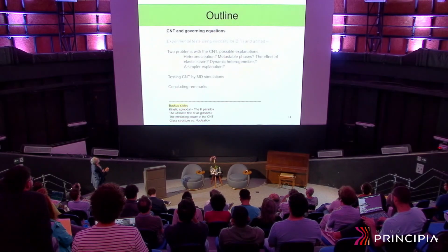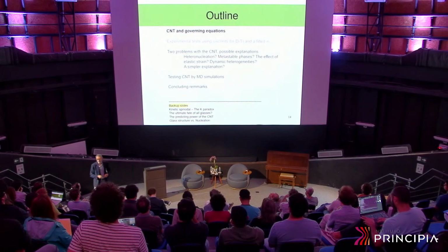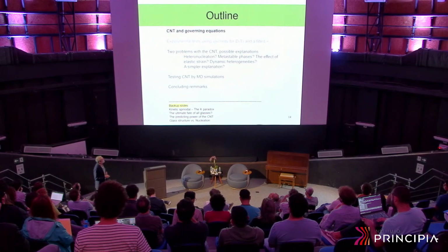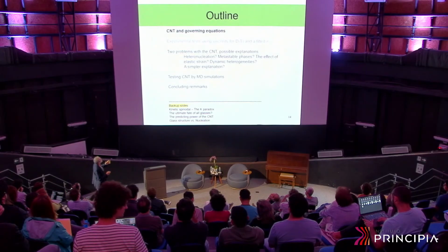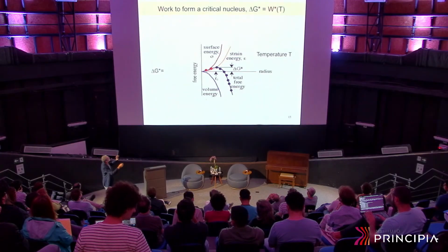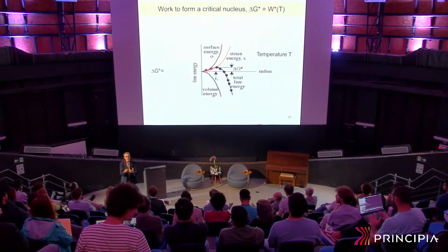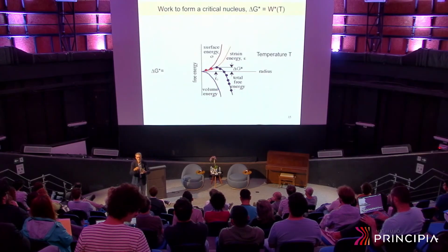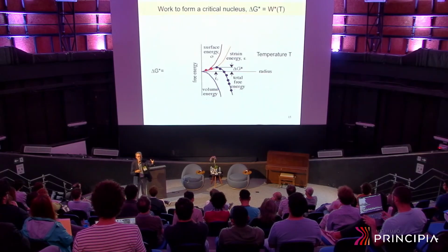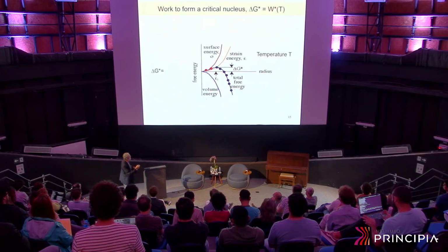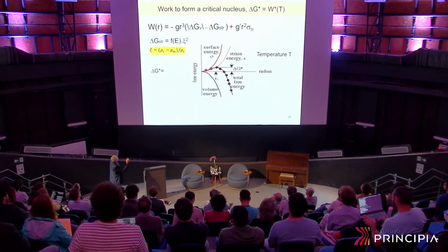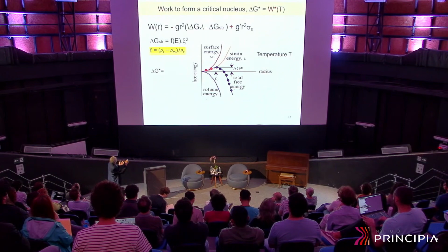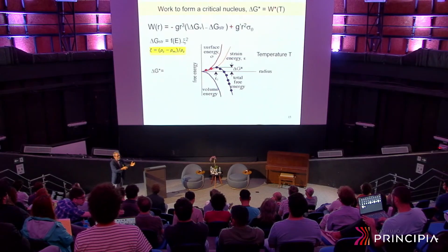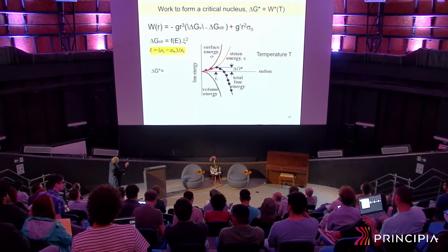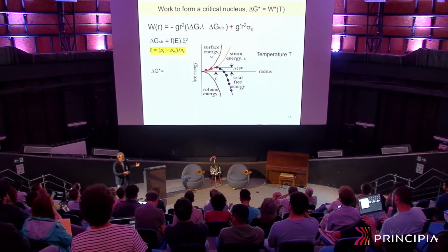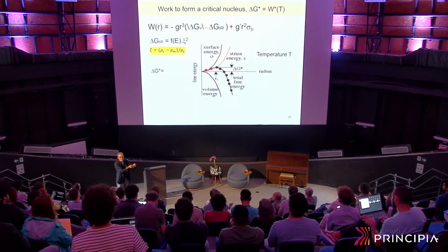Anyway, there are several theories to understand the early crystallization stages. The classical nucleation theory is a very friendly theory that many people use. The theory is very simple but elegant. If you have a supercooled liquid, you wait a little bit, and heterophase fluctuations will form and dissolve. This equation, from Gibbs, gives the thermodynamic work to form a critical nucleus of radius r. Let's assume they are spherical for simplicity. You have a positive contribution of the surface energy, because if you have a crystalline nucleus, you have a new interface forming in the liquid, so you have a